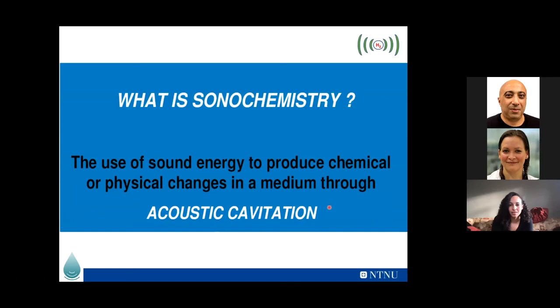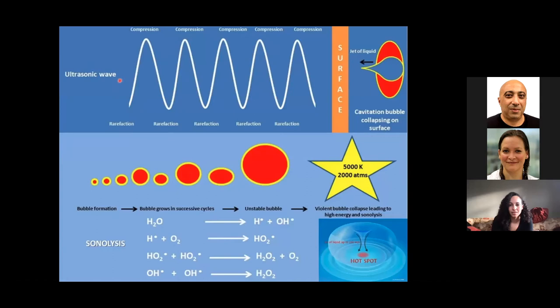So you have a sonic wave propagating through a solution. You've got zones of compression and rarefaction. And imagine that you're doing that at 20 kilohertz, 20,000 times per second. So you're doing quite a lot to the solution, and you're creating cavities. All those cavities tend to grow, reach an unstable radius or stable size, and then they collapse. Upon collapse, they produce jets of liquid of around 20 meters per second, sometimes 200 meters per second, close to the surface. And it has been reported that you can produce, upon cavitation implosion, 5,000 Kelvin in temperature and 2,000 to 5,000 atmospheres in pressure.